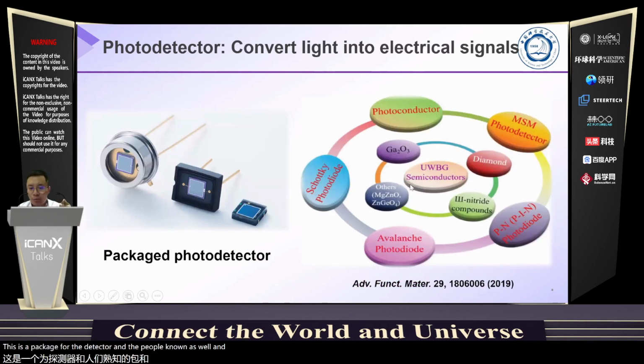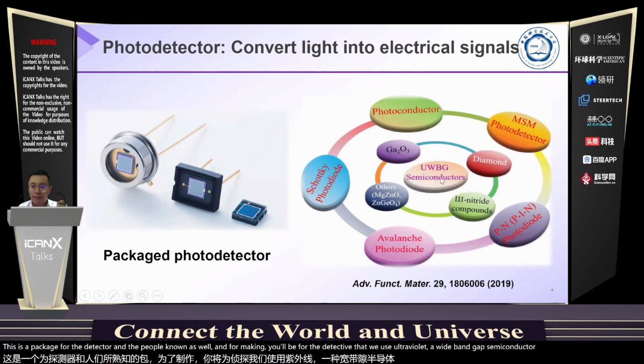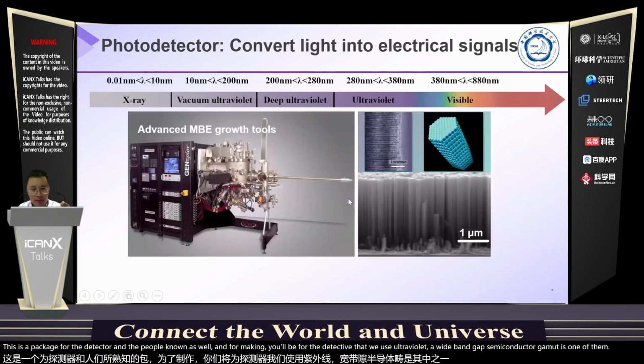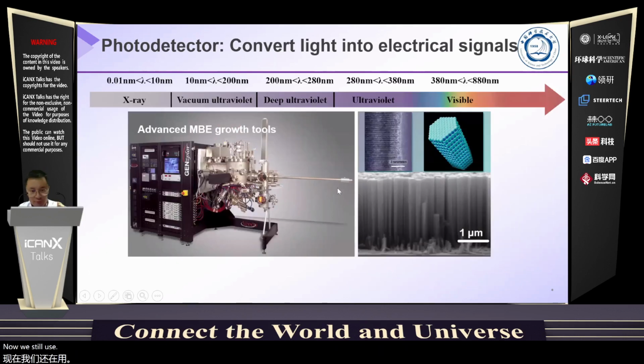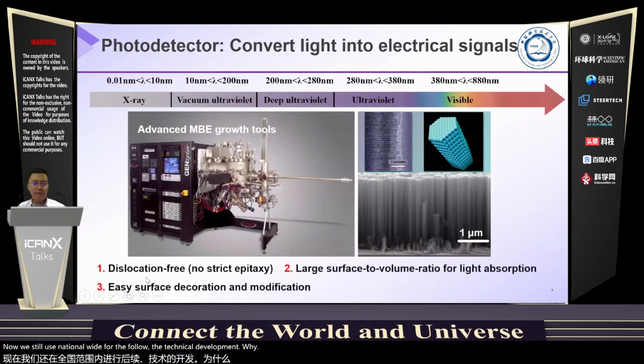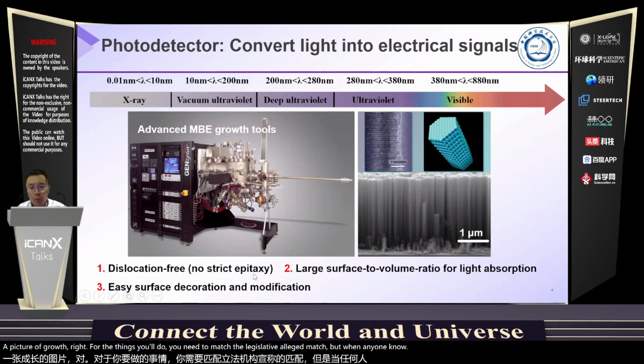For making UV photodetectors, we use ultraviolet wide bandgap semiconductors. Gallium nitride is one of them. In our group, we still use nanowires for photodetector development. Why? Nanowires have a dislocation-free property and do not require strict lattice-matched growth. For thin films, you need to match the lattice, but for nanowires, no. We can grow them on metal, on silicon, on sapphire, or any substrate.